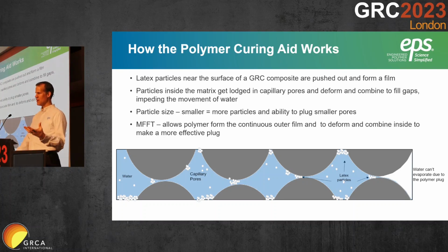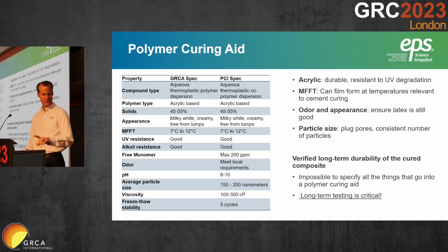It doesn't do a perfect job because there's a lot of pores in concrete. But adding 5% lowers that diffusion and the ability for the water to leave enough to keep the water in there well enough to give it the full wet cure. Now, let me see if I can go back. Yes.